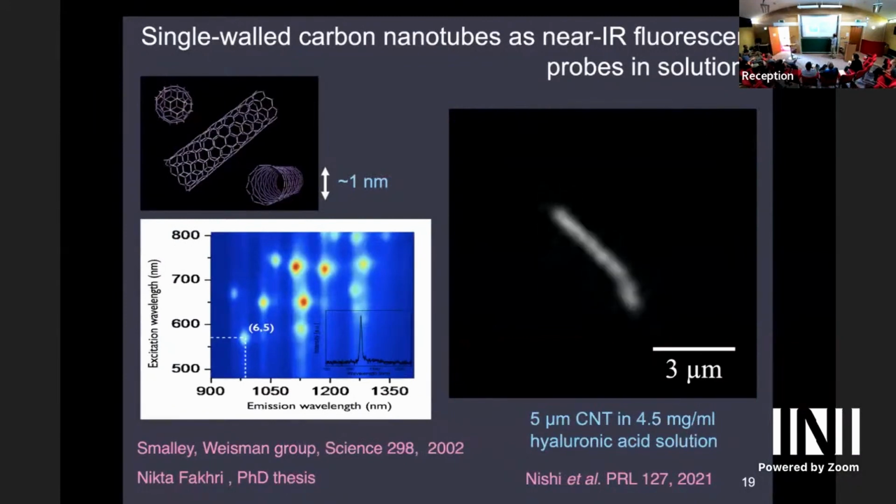And of course, the driving force here is just thermal fluctuations. So there's no active force in this case, and so it's fairly straightforward. But the advantage of using a structure like that is that these have extremely high aspect ratios, like 10 to the 4 or so. So they're very thin, and they can get into anything. They can get into the cortex of cells.